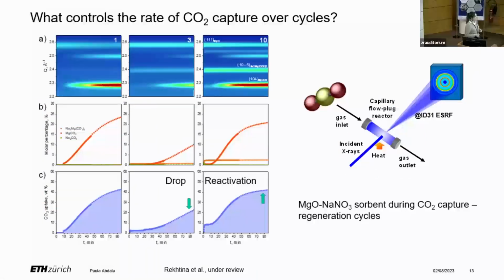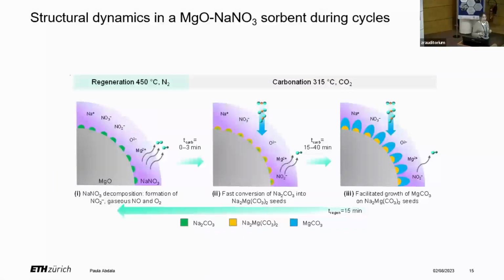So with additional techniques, we studied this with in situ Raman spectroscopy. We learned that the molten salt, when we regenerate the material at 450 degrees, starts decomposing, which accumulates over cycles, and this decomposition product reacts with CO2 and magnesium to produce this double salt. And this leads to an increase in the performance.